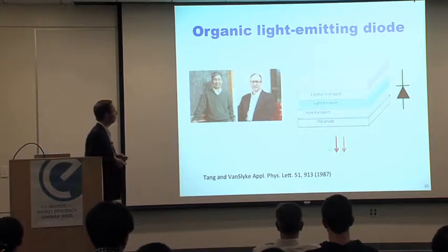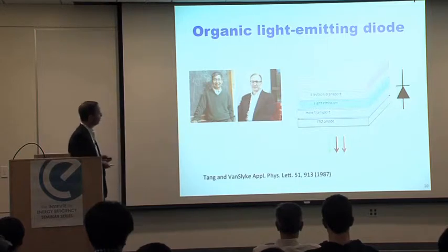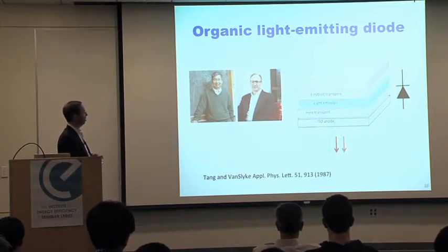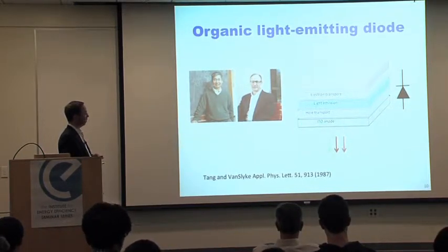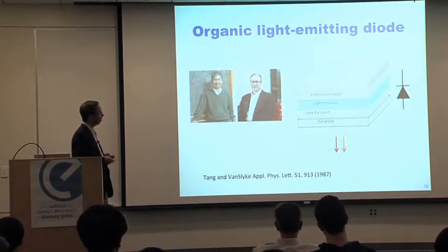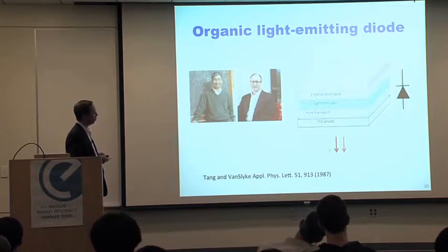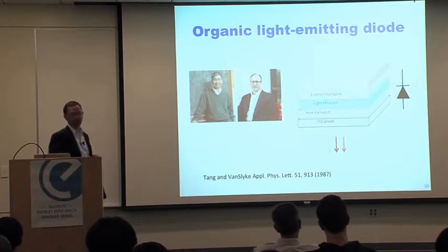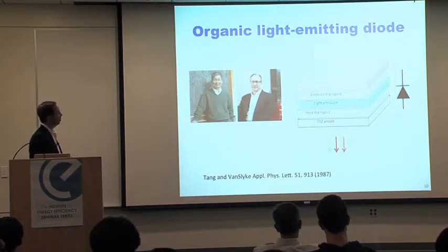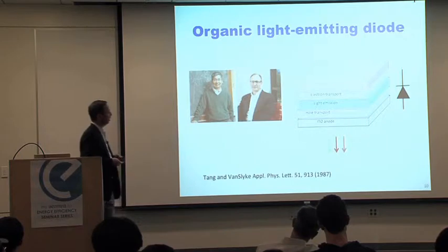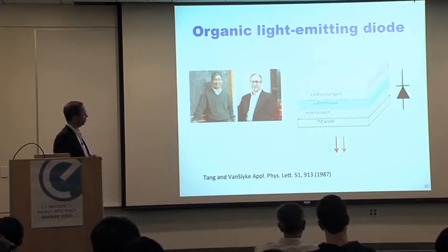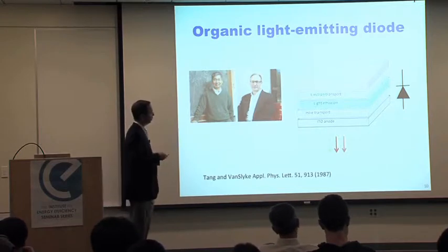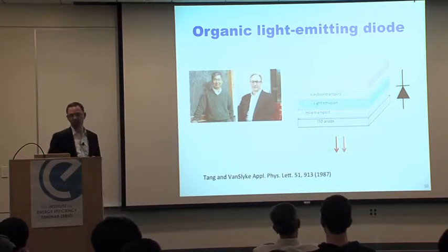And so that kind of started to get people's attention. And the general structure of devices like this is shown here on the right-hand side. This typically has the structure of a diode. You start with a piece of glass which is transparent, which is coated with indium tin oxide, a high work function electrode. You deposit a few layers, one for the injection of holes, one where the holes and electrons create excited states, and the relaxation of these excited states back to the ground state leads to light emission, and the light is usually emitted through that transparent substrate. And for the injection of electrons here on top, you have that low work function electrode.